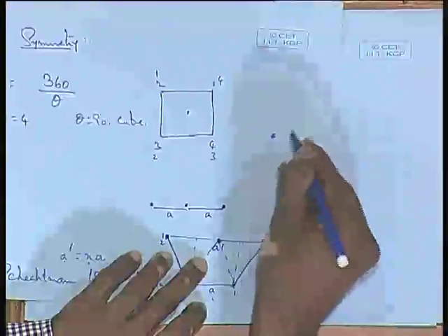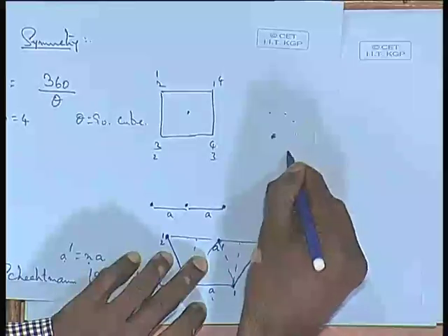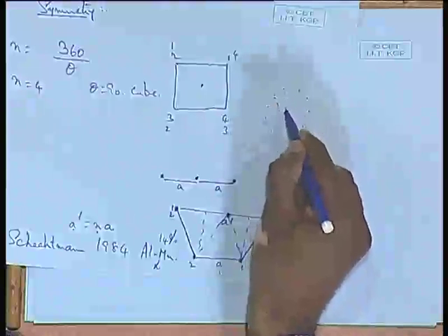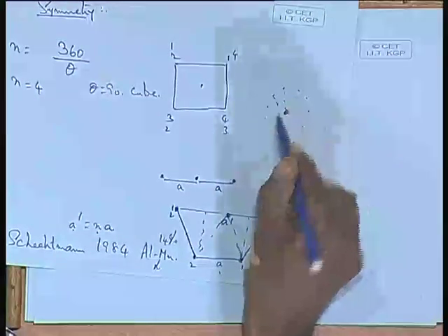The diffraction pattern looked like this. It has a transmitted spot and it has 10 spots around it. It is like a 10-fold symmetry, all spots are equally spaced. That means, if you think of the angle between these two spots with respect to the transmitted beam, that angle is 36 degrees, which is the same for all of them. So, the diffraction pattern looked really strange, which had never been observed in any material till then.